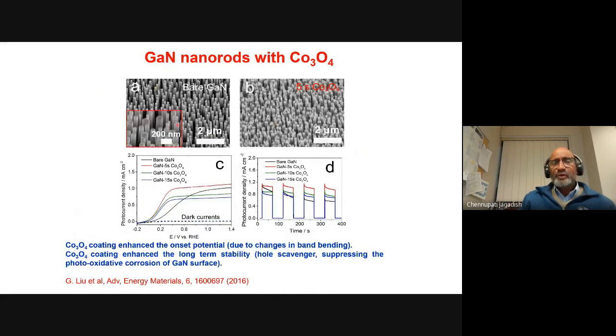So based on that one, we've looked at gallium nitride, and this is the work of my former student, Dr. Reddy, and also Dr. Liu from engineering. Reddy has made these gallium nitride nanorods and coated them with cobalt oxide as a co-catalyst and also stabilizer. By using cobalt oxide, he's able to show that you can get a stable performance from these gallium nitride nanorods. Normally, gallium nitride is very difficult to etch chemically.